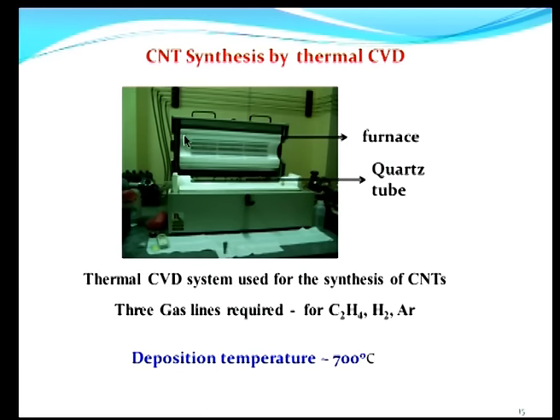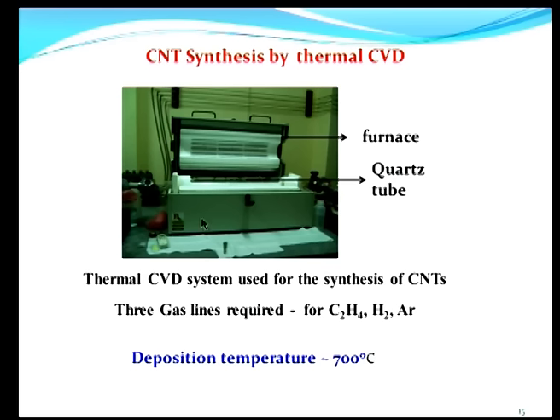This is actually a piece of apparatus — a chemical vapor deposition reactor, thermal CVD — where only temperature is used to conduct the reaction, as opposed to plasma CVD where a plasma is employed to accelerate the process. In this furnace one places the substrate and then uses a gas — for example, ethylene C2H4, hydrogen, and argon — following certain protocols to deposit carbon nanotubes on a substrate like silicon at a temperature of about 700 degrees Celsius.